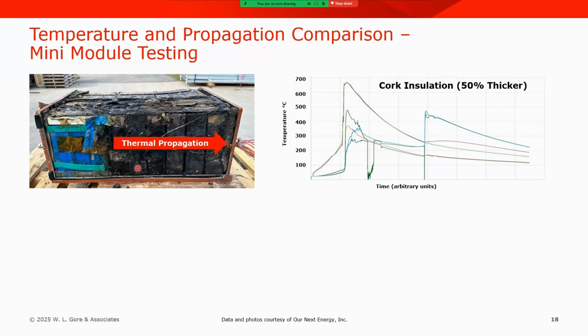As you can see here, the center cell was placed into thermal runaway. That thermal runaway propagated, of course, to the cells on the left and the right, but it then also jumped over the thermal barrier layer and was able to propagate all the way to the end of the module. In addition to the visual evidence, the thermocouples also show that even the most remote thermocouples are well above 150 degrees C, in some cases approaching and even exceeding 300 degrees C. So this is a non-ideal result from this thermal runaway propagation test.